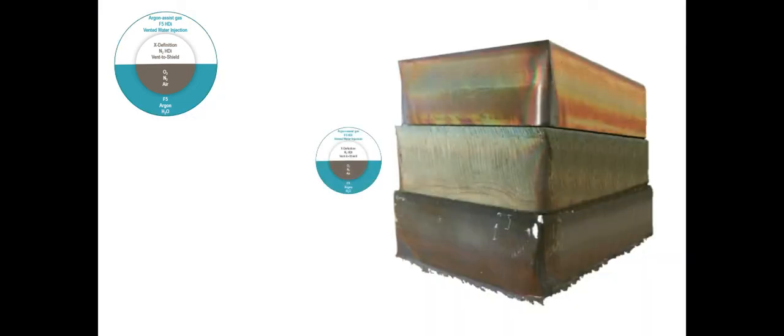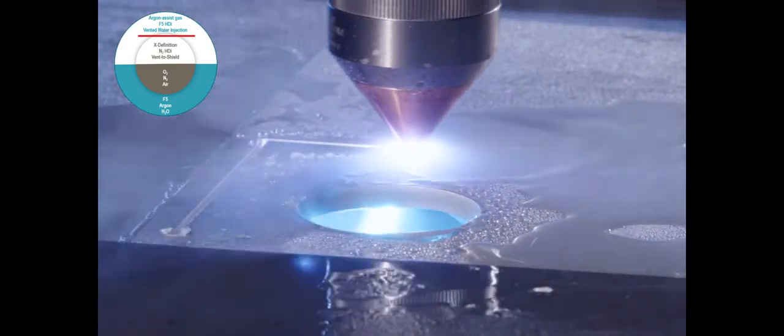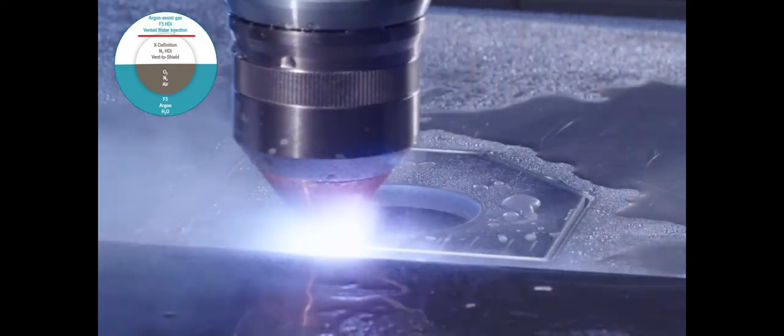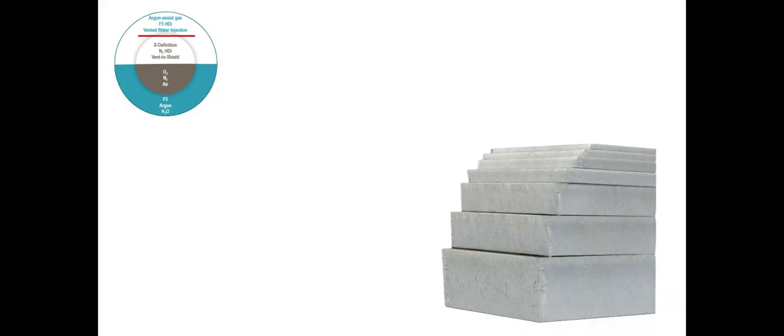Thick stainless steel cutting using vented water injection improves surface finish when comparing to the core console, but is further improved when using the OptiMix console. Vented water injection technology can also be used to cut aluminum. This process provides a smooth cut surface and is optimal for a material range of 6 to 50 millimeters or 1/4 to 2 inches over a variety of different amperages, 80 to 300 amps.